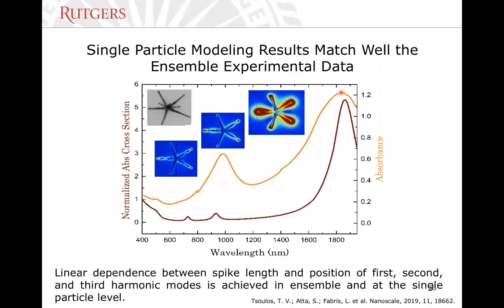These types of applications. What is also interesting is that if we collect spectrophotometric data of these particles and we look at the experimental ensemble experiments, what we see there is a relatively nice match between the position of the spikes. There can be something to be optimized. We can narrow the width of the spikes, but from our standpoint, we believe this is a nice result that we were able to achieve.